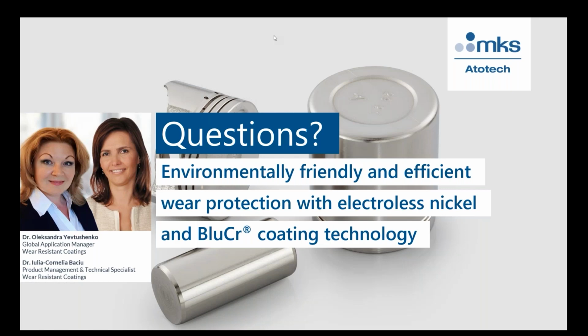This will cause micro cracking in the structure, and this will provide potential sites for direct access to the substrate. It can be seen as damage and a decrease of the corrosion protection of the coating. Thank you very much. Corrosion protection will decrease after heat treatment.